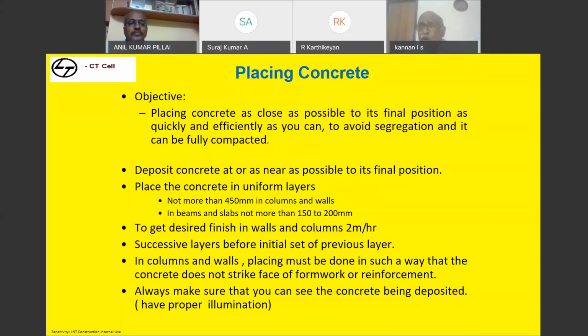In the same way, reinforcement also should not be struck, because when the concrete touches the reinforcement, segregation can happen. Okay. So make it a practice. Suppose you are placing concrete, have a plywood on the side, pour concrete on the ply, and allow the concrete to flow through the cover zone, because the minimum cover we have is 30 millimeter or 40 millimeter and your maximum size of aggregate is only 20. Easily it can flow. Have an inclined ply just outside the form, pour the concrete through the ply, and let it go through the cover zone so that the concrete flows easily and you are also able to compact it well.